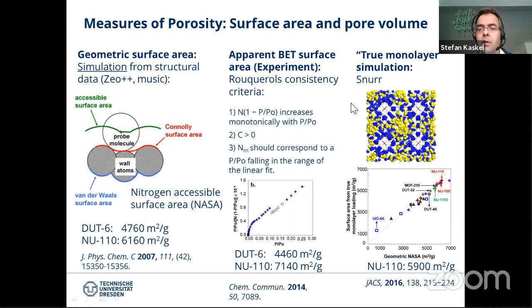And Randall Snurr pointed out what the reasons for this are. That is basically that we have to simulate what is the true monolayer coverage, essentially, in his paper. And so he developed a method to simulate the true monolayer coverage, which is normally derived from the BET equation and from the isotherm. And this is another way, basically, to characterize the material to give an apparent surface area as the true monolayer coverage.